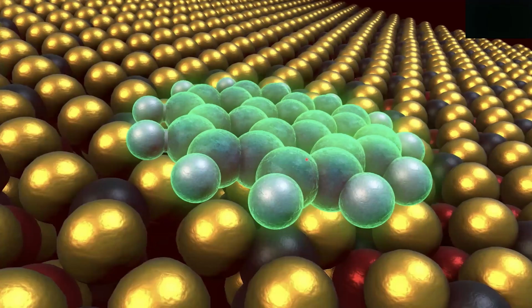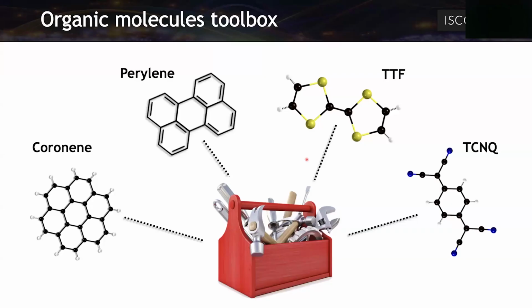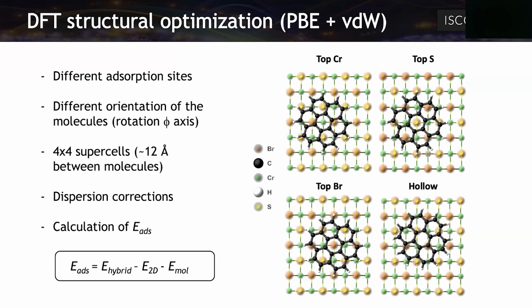But we are also tuning directly the properties in the 2D material. That's important. We have started studying these organic molecules. We have focused mainly on donors because we have chromium sulfur bromide, which has these bromide atoms that have high electronegativity. And we have been studying coronene, perylene, and TTF, but we also wanted to test an acceptor, in this case, the TCNQ. This is the first work towards this molecular control of magnetics.